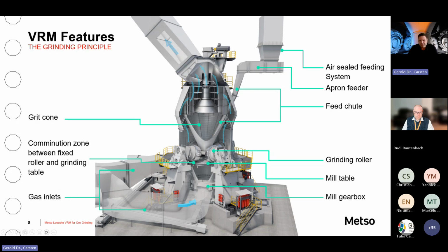The grit cone has two jobs. On the one hand, it optimizes the gas flow to the classifier. It's a high efficiency dynamic classifier, which you see on top. At the same time, everything that the classifier rejects is guided back to the center of the grinding table, where it's recombined with a fresh feed. So we mainly have an internal grinding classifying circuit.